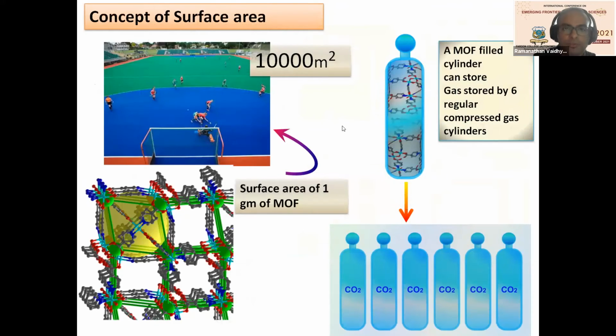Now, to give you a feel for it, what is the surface area I'm talking about? So for example, 1 gram of a MOF can have a surface area of 10,000 meters squared per gram, which is equivalent to an entire hockey field. Okay, so that much surface area can be generated by 1 gram of MOF, which means if a small molecule starts to fill this hockey field, you can imagine how much of the hockey field's surface it can fill. That much, 1 gram of MOF can adsorb and fill.